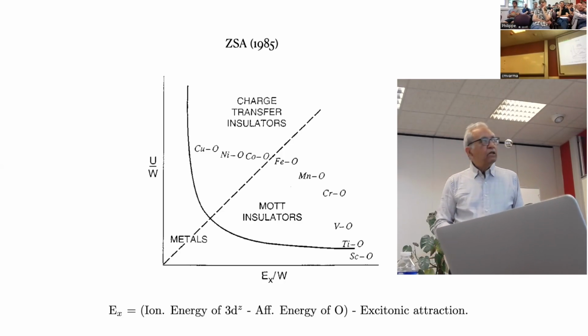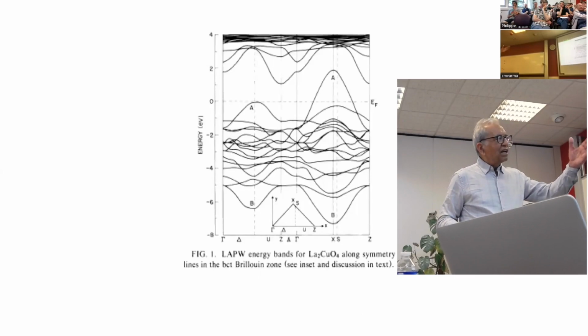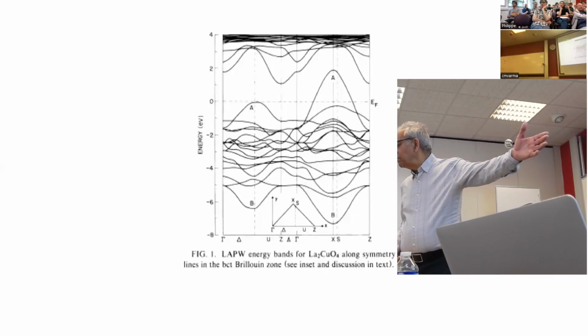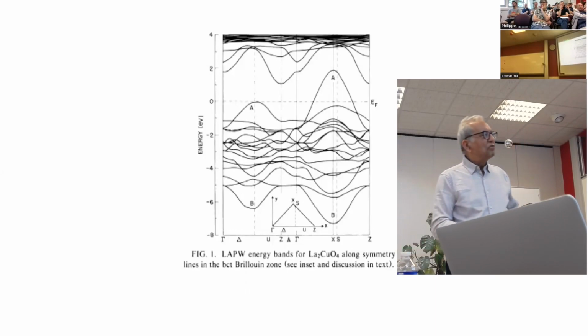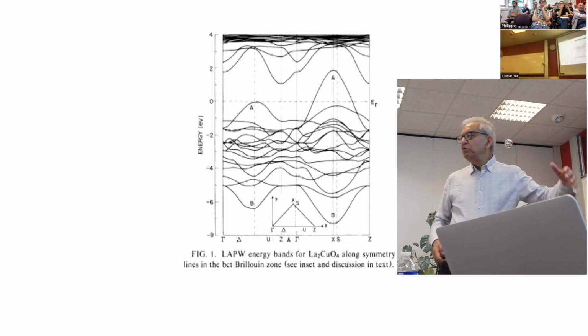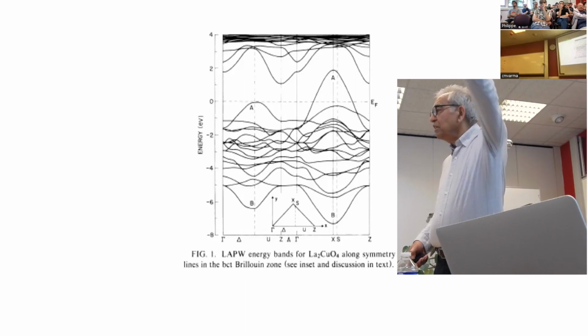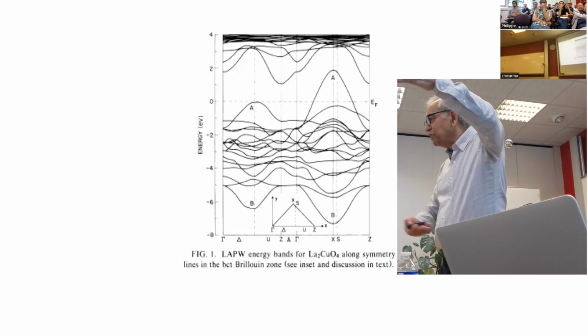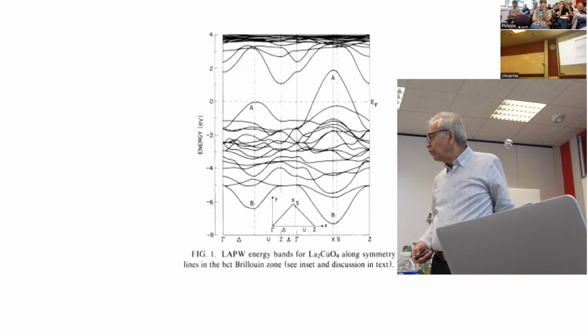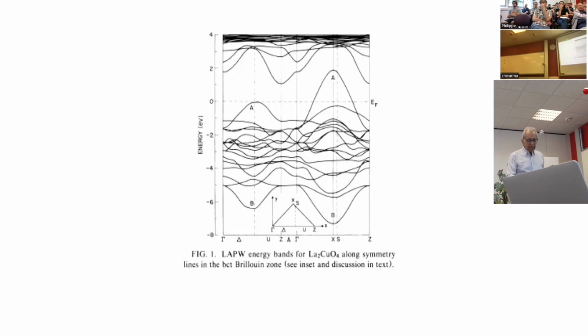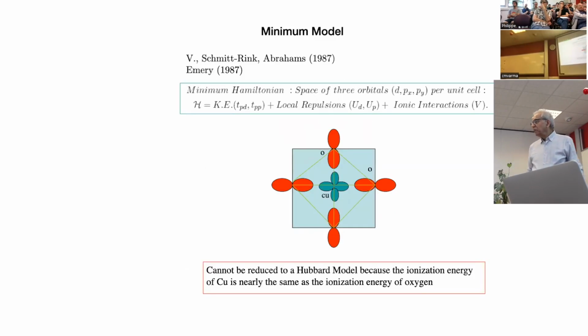Okay? So this was also present there. Mattheiss did the band structure of copper oxide cuprate within a month of the discovery, and you see that the copper and oxygen levels are completely intermixed here. If you were to do it for, let's say, vanadium oxide, you'll see vanadium levels here and oxygen levels down there with the 3 or 4 volt energy difference. But here they're all mixed in.